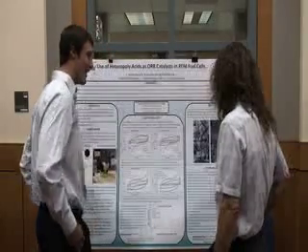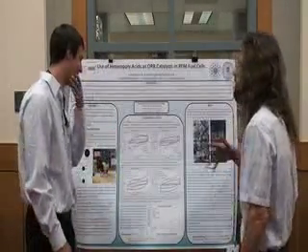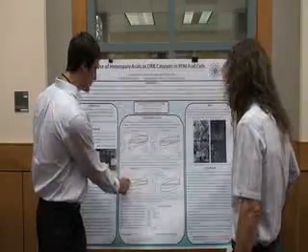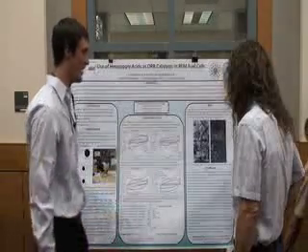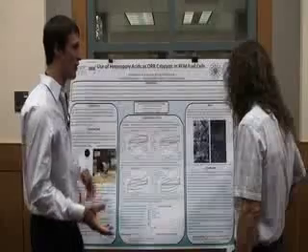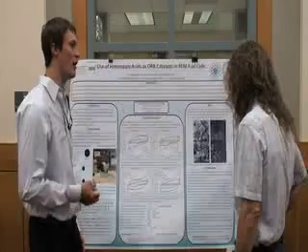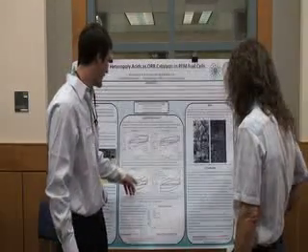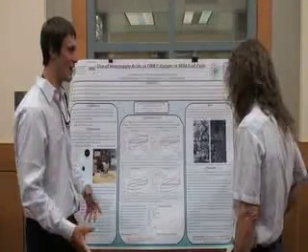Oh, okay. So that's the problem, we were hoping that. You're hoping it would be better. That's definitely right. We were hoping that when we add these, we'd still have the nice big oxidation reduction curves, but for whatever reason, they suppress those abilities. And I don't know if it's due to the morphology, diffusion, or what it is, but that could be further tested with more imaging research. And this tells us that when we put platinum with the PMo11, there was actually a decrease in the diffusion rate, which is kind of odd.